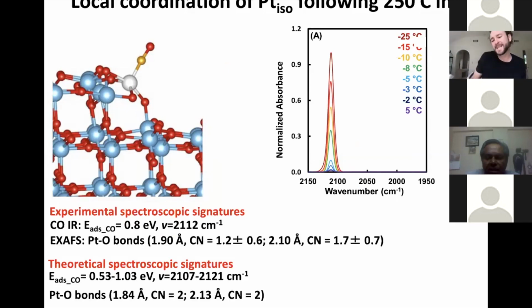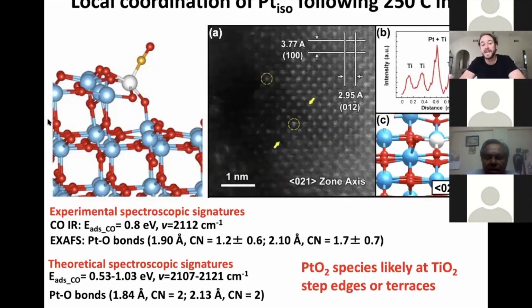We can also look at XAFS, and I won't go into this here. I'll mention this in a couple minutes to show that our structural model here is consistent with a structural model we would derive from an XAFS measurement. And then extremely convincing is if we took this DFT model and we spun it to orient it along a 0-2-1 zone axis, you would find this platinum atom here lines up perfectly with a column of titanium atoms underneath it. And then if we go do aberration-corrected transmission electron microscopy, what we always find is that the platinum atoms are orienting themselves just above or in line with titanium columns when we're along the same zone axis.